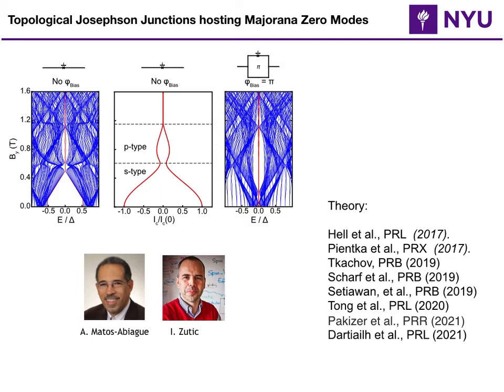So if you look at the red graph on the left side, you see that the red closes around 0.5 Tesla and stays around zero energy. In a Josephson junction, we don't measure energy, right? We typically measure supercurrent. So if you translate this spectrum to the supercurrent that you expect to see, these calculations are done by Igor Zutic and Alex Matos-Abiague, you expect the supercurrent also to show some qualitatively similar behavior. The supercurrent decreases and then reopens, and that signifies a transition.